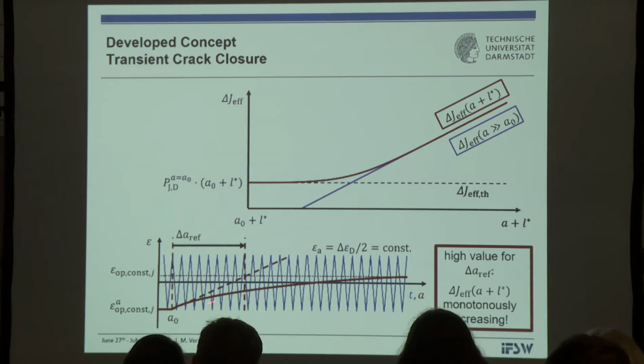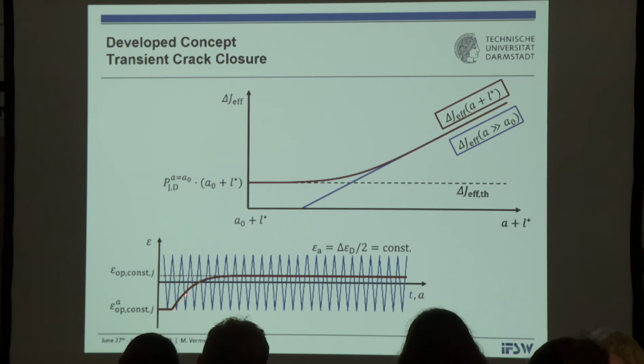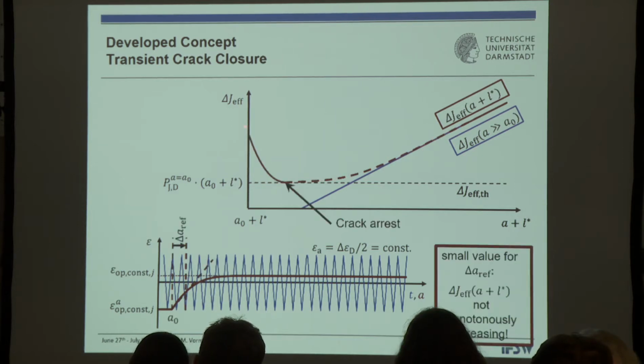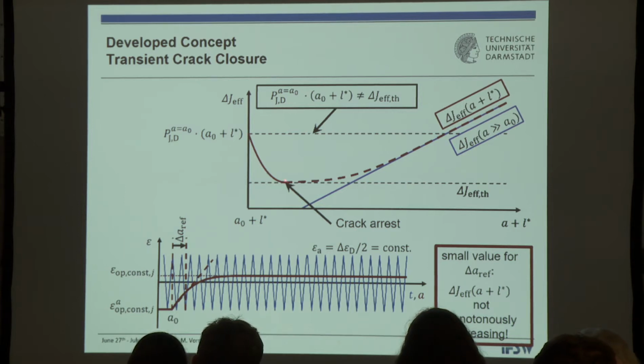of the crack surface and with it the crack opening level here is very, very slow, then you can identify in a graph where you plot the associated delta J integral over the crack length that although the effective ranges here become smaller and smaller due to the longer crack, the J integral is continuously and monotonously increasing, and you are faced with this situation as sketched in the upper figure here. However, if this process is taking place very quickly, then the effective ranges are decreasing also very quickly, and you end up with a situation that with the growing crack, the delta J integral is decreasing and it can fall below a threshold value, and then you have crack arrest.